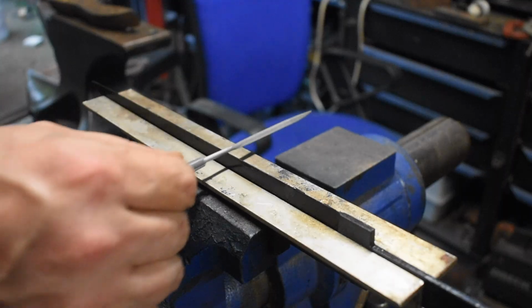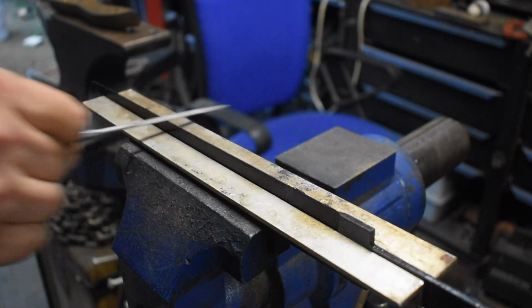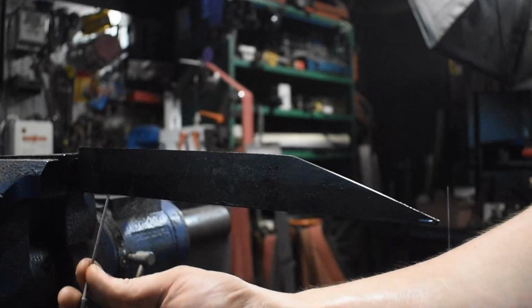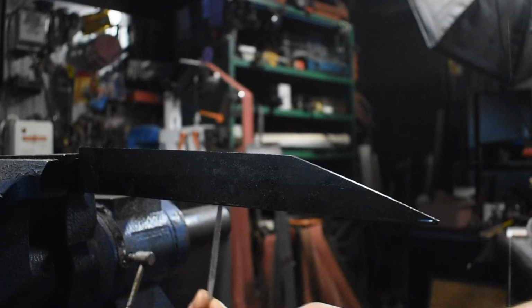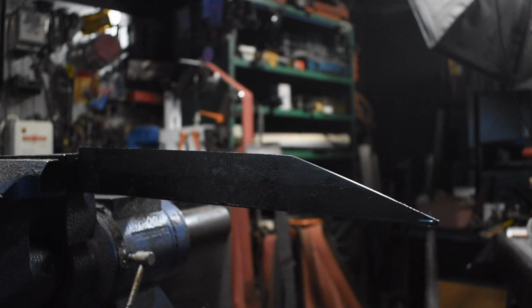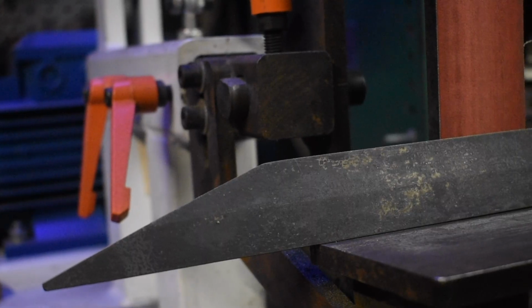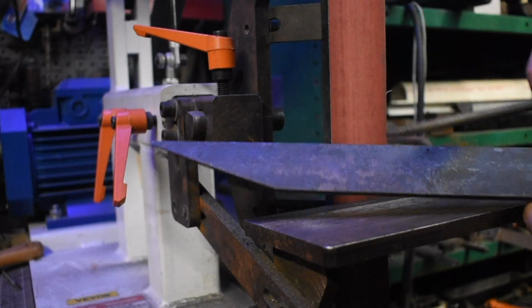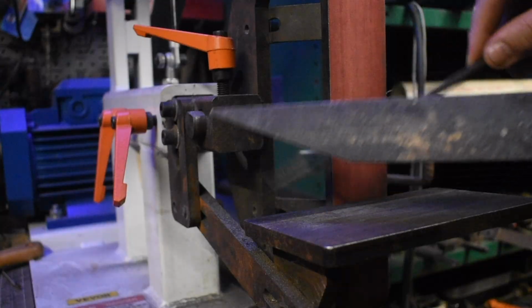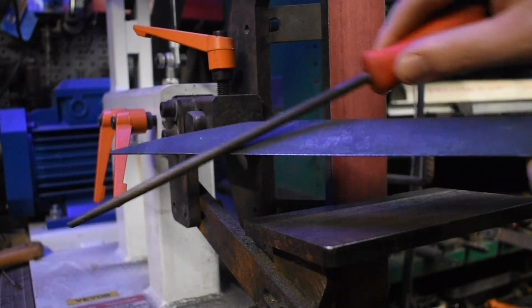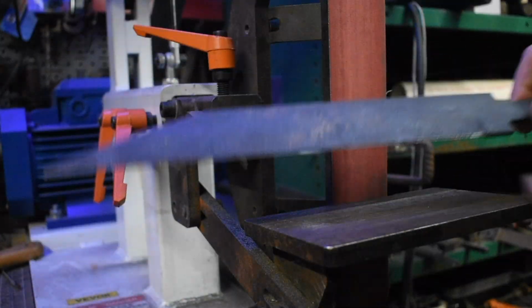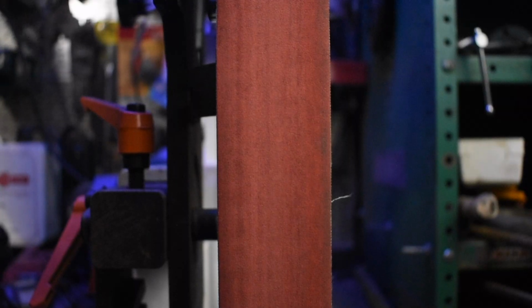To help prevent a warp, I put it in the vise with the angled aluminum pieces and let it cool down. And then I tested it with the files and everything skates really well, so I'm pretty happy about that. So I put it in the oven at 400 degrees for about an hour and a half to let it temper back some. And then I test it with the file one more time and everything seems to skate good. So now I can move on.